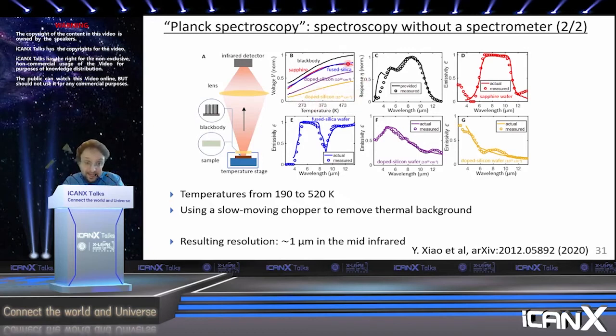We take this data and apply an inverse algorithm to try to figure out the best fit to the emissivity. The first thing we do is figure out our system response, which really just means the responsivity of our detector multiplied by the transmittance of the lens. So we put this black body here, whose emissivity we already know. We do the measurement, and from that we figure out the responsivity of the setup, mainly just the detector response. So this is the detector response versus wavelength.